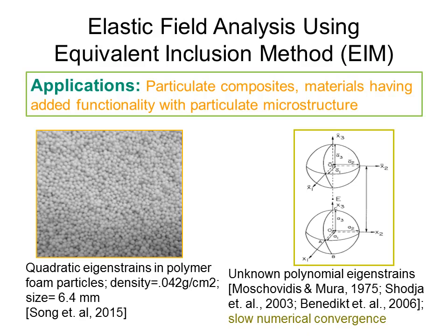Because of the elastic interaction, the eigenstrains cannot be uniform. This is a good approximation. However, if you want to calculate the exact solution for interaction between two elastic inclusions, then you have to take several higher order terms.